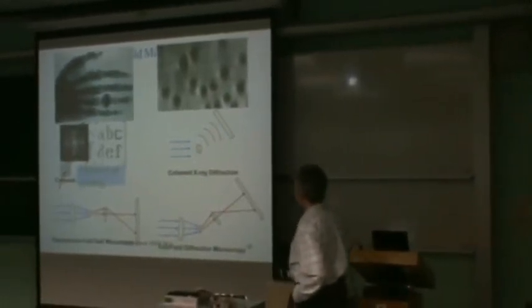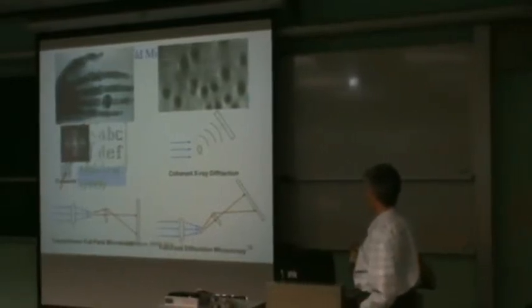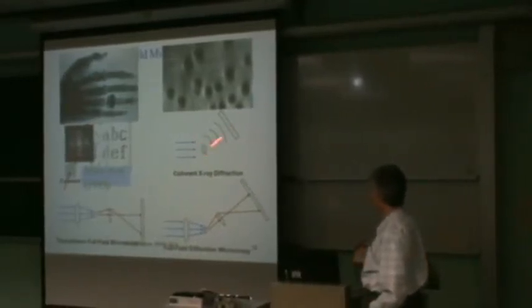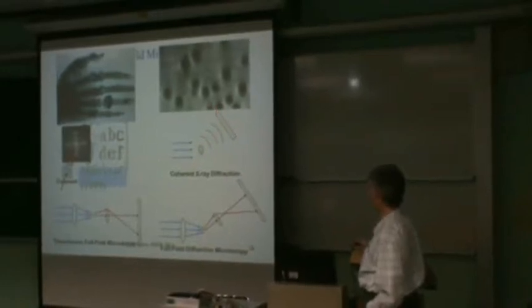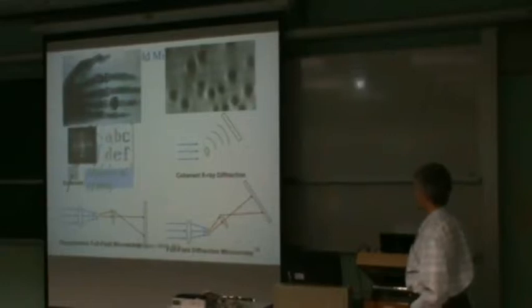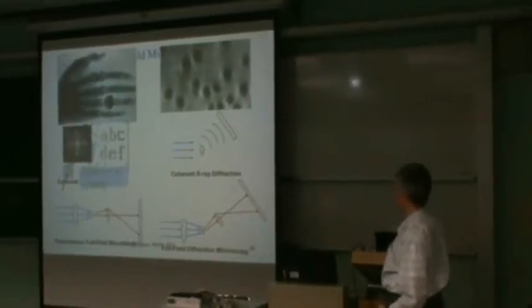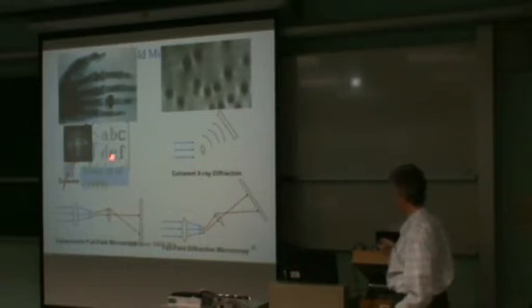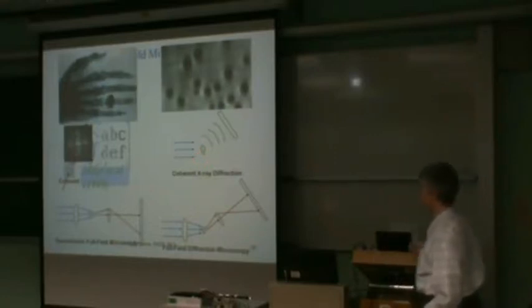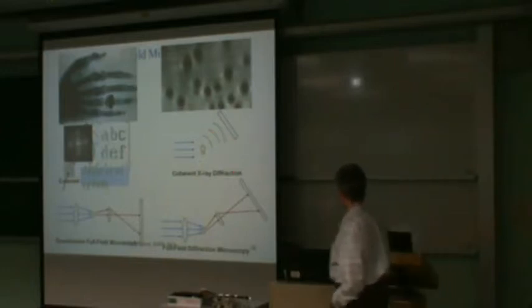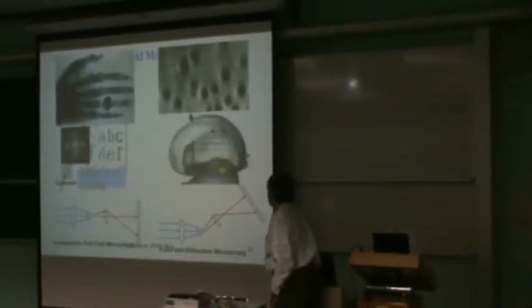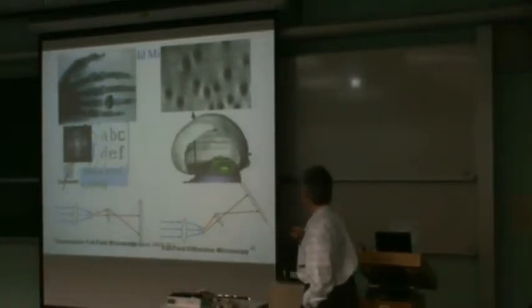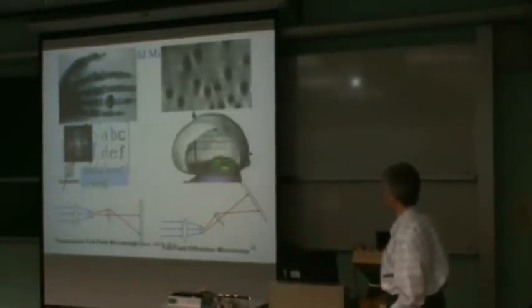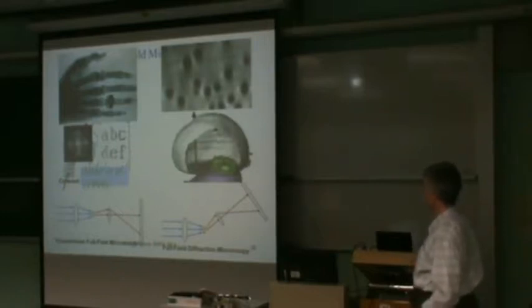That also converts into a diffraction version. This would be a Bragg diffraction version where you look at the Bragg peaks coming from the sample that you're looking at. You measure them with a finely spaced detector far enough away that you can oversample the diffraction pattern. And by the same analysis method, you can get images of the sample with the additional possibility of measuring strain. And this is the method I'm going to concentrate on most today because it's the one that I've been using the most. And that one, it's an older example, but this is showing a strained, distorted image of a small lead particle.